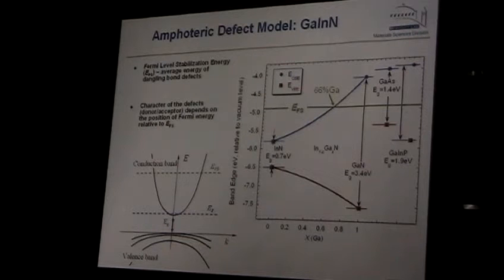And the way it works is that when we take indium nitride, slightly n-type, the Fermi energy is here. This is the conduction band. We start to irradiate it, and we produce more and more donors, and the Fermi energy goes up to this point here. When we take gallium nitride or gallium arsenide or gallium indium phosphide, most of the semiconductors, then of course the stabilization energy is in the band gap. So in this case, when we start with n-type material, the Fermi energy is in the conduction band, and in fact the Fermi energy now goes down to the band gap. So it shifts, and we knew what to expect in this case.